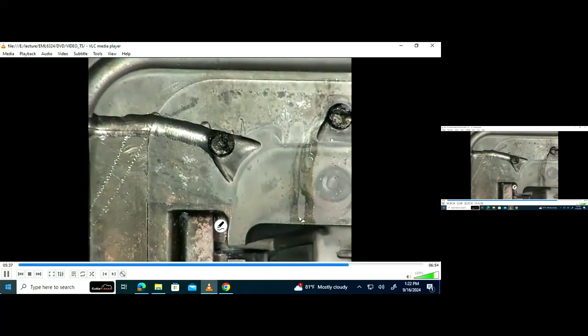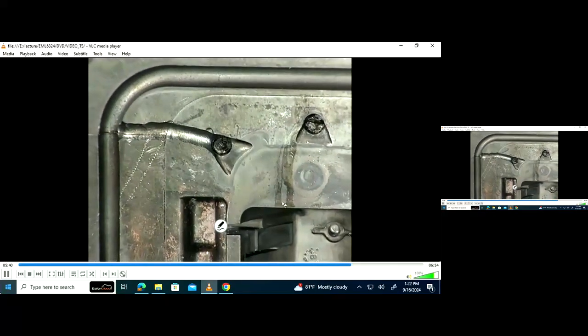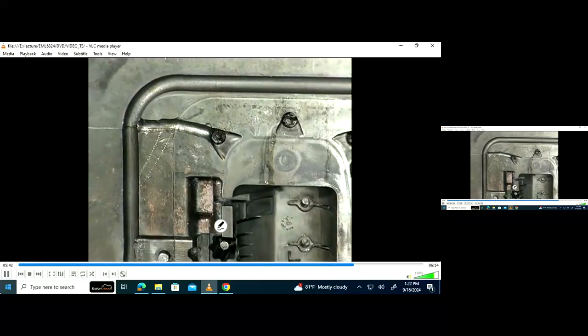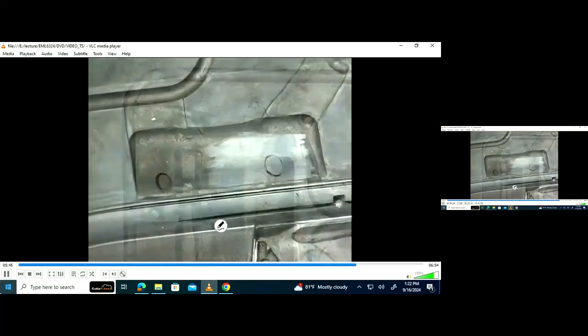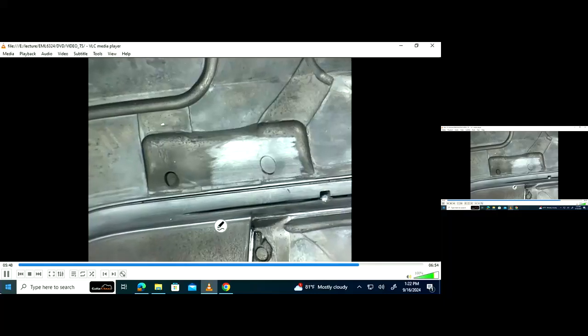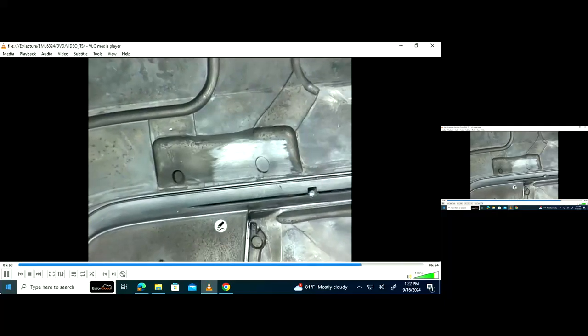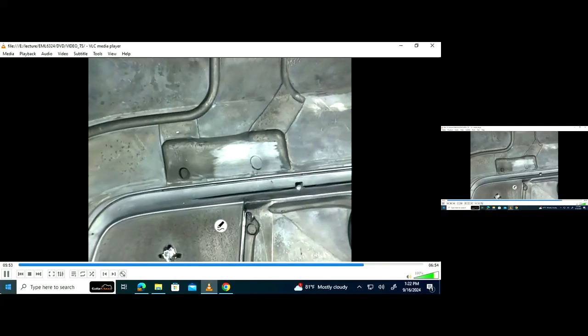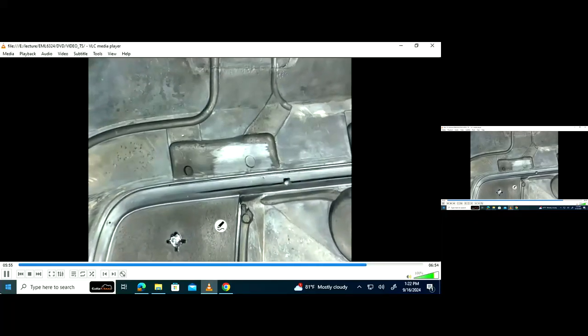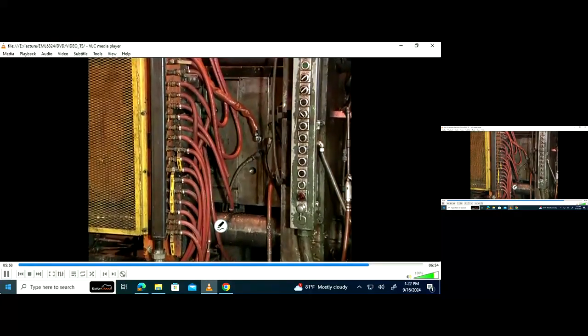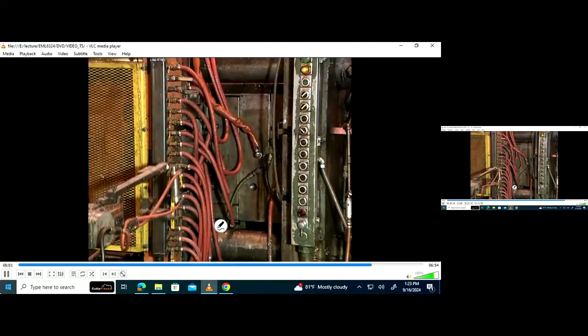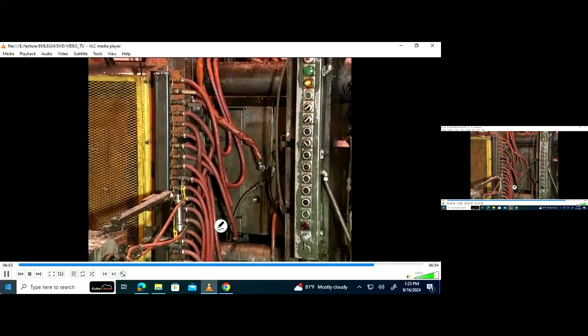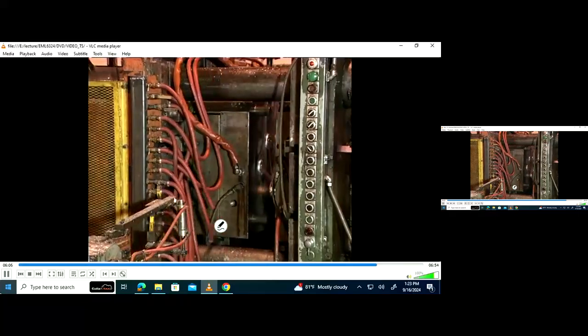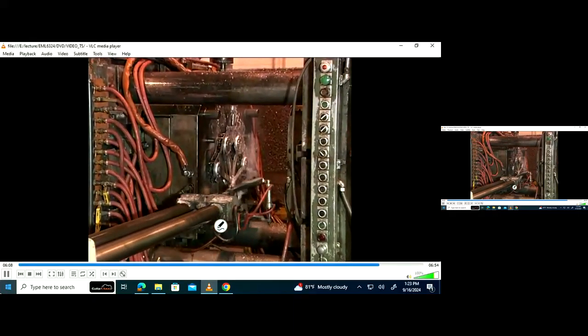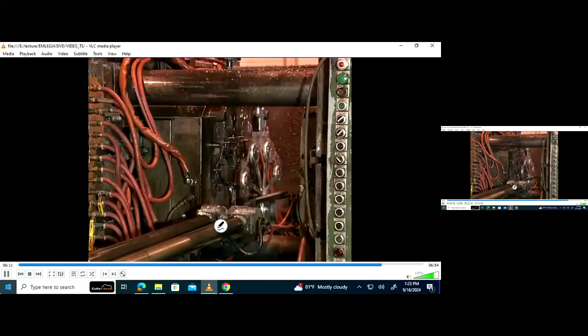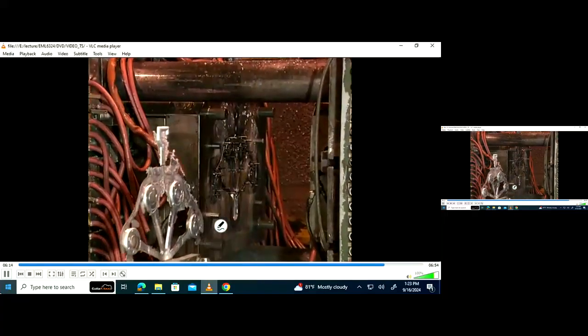To minimize porosity in the casting, the die halves have vents to release the air that is pushed ahead of the metal shot. Overflow channels in the die blocks catch surplus metal. They also assist in venting and provide locations off the casting for its ejection. Built into the die blocks are cooling lines, circulating water or oil to dissipate the heat of the molten metal at a precise rate. Cooling at a controllable coolant flow rate is important because it controls the metal solidification rate.